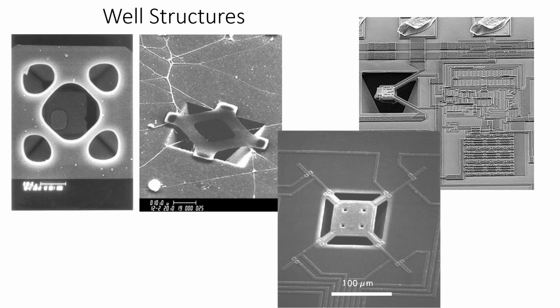Using this inverted cavity trick, you can create a lot of interesting structures, such as this cavity with a grid on top, or this one, or something like this. Here you can actually see that the cavity has an undercut because this edge appears to be white. It's white because the scanning electron microscope produces electrons that charge the mask, which is non-conductive. Here we have piezoresistors on this side. Or you can create free beams. This is fixed-free beams. So this is a very interesting trick.